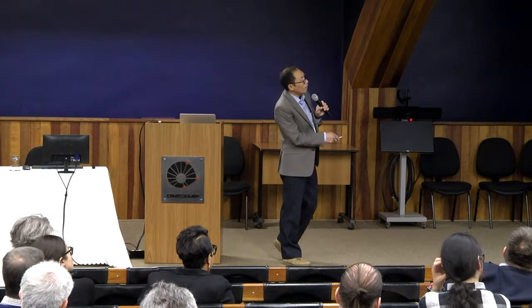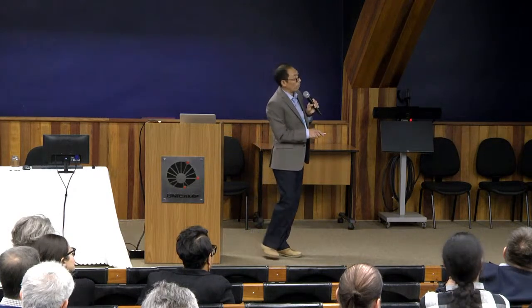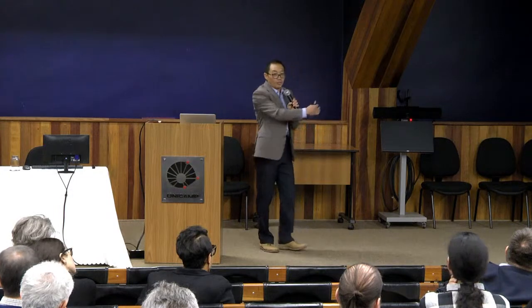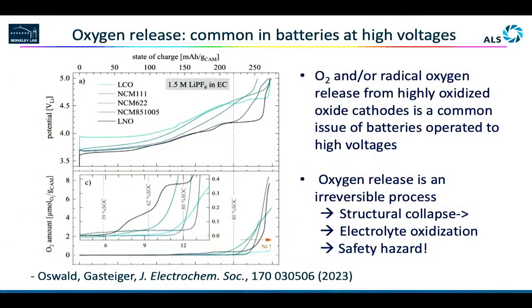This is lithium nickel oxide. LCO is lithium cobalt oxide. Those are nickel, cobalt, manganese compounds. There are all kinds of different oxide materials. If you cycle it up to beyond, for example, 4.5 volts, then you will see the rise of this, which is the oxygen gas coming up. I just randomly pulled out a recent paper by the Gasteiger group, a famous group working on this kind of technique. It's called differential electrochemical mass spectroscopy. So you will see the oxygen release from the material if you go up to certain voltage.